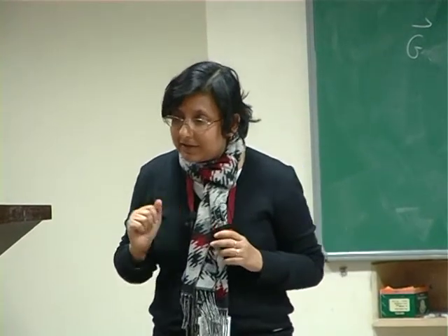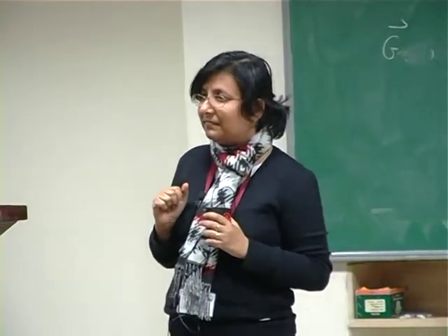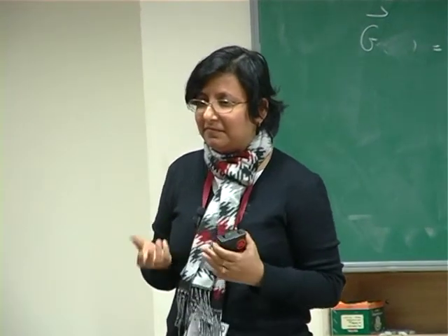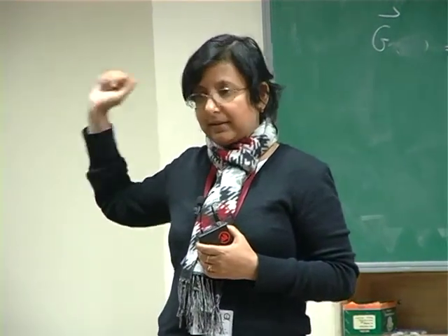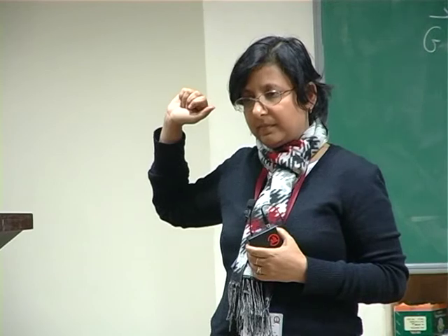Can I comment at least on Vijay's point? If you take the mercury compound and the thallium compound, one is tetragonal, another is body-centered tetragonal. So the link between different layers should be very different between body-centered tetragonal and tetragonal, but their TC is the same, 90 Kelvin. In fact, the Kz dispersion for thallium should be much less compared to mercury. That's the correlation between your parameters. But the correlation in that case is with the TC max. No, if you plot it with respect to T star, it will be a better correlation. That's all I'm trying to say.